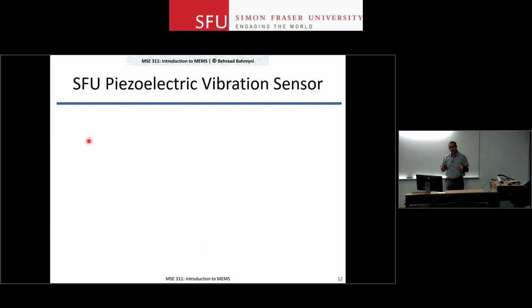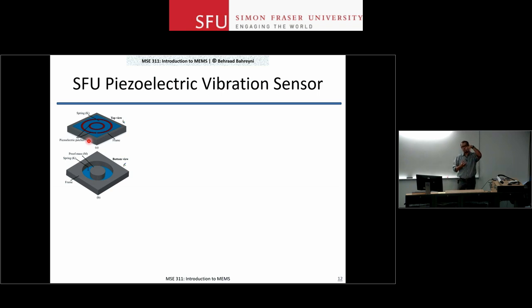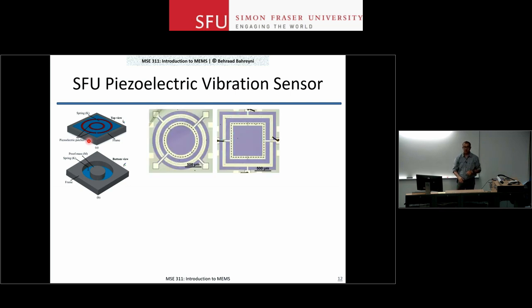And then once more, I want to show you one device that we've made at SFU. It's a piezoelectric vibration sensor. What we're doing here is that we have a layer of piezoelectric material on the top of the wafer. We keep a portion of the substrate behind the membrane, so that acts as a proof mass for us. The membrane itself will be our spring. And now when you have vibrations in the environment, this goes up and down, and you produce stresses and strains on the piezoelectric layers. They're underneath these electrodes. You cannot see them, they're under the electrodes. But then we have the electrodes here to collect that charge and measure it.